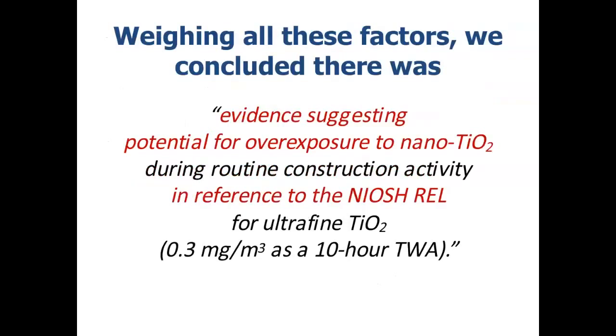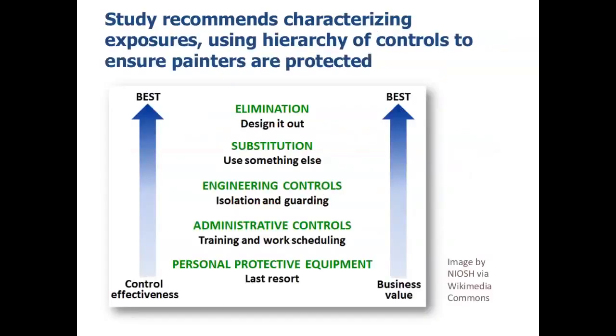So what does this all mean? We weighed all these factors together, and in the paper we concluded that there was evidence suggesting potential for overexposure to nano TiO2 during routine construction activity in reference to the NIOSH REL for ultrafine TiO2. Again, that is 0.3 milligrams per meter cubed as a 10-hour TWA during a 40-hour work week. So the recommendation was to characterize exposures and to use a hierarchy of controls to ensure the painters are sufficiently protected.